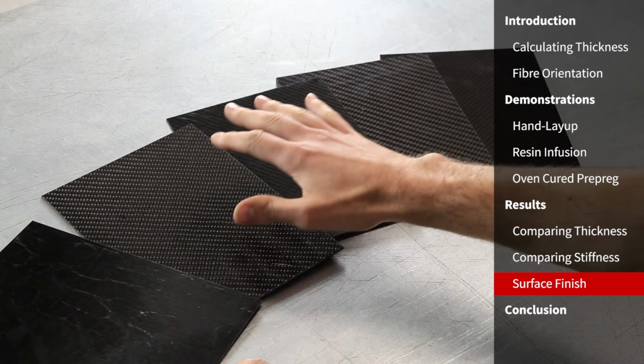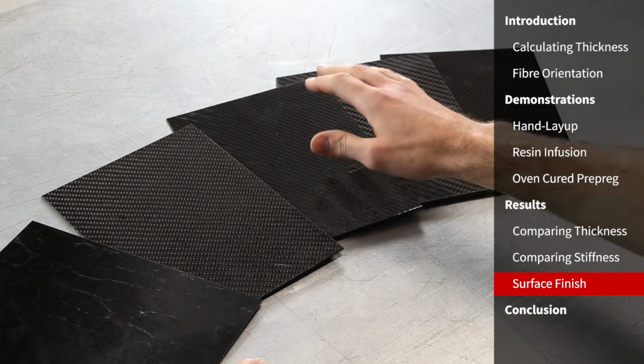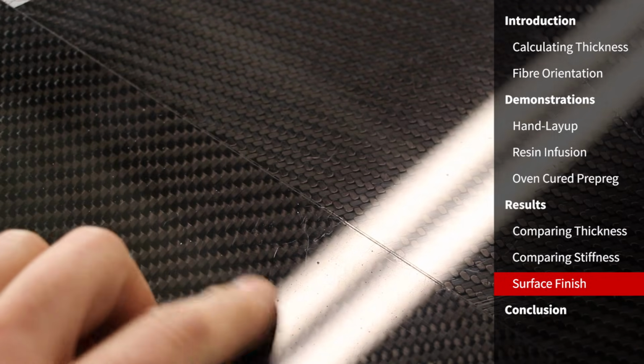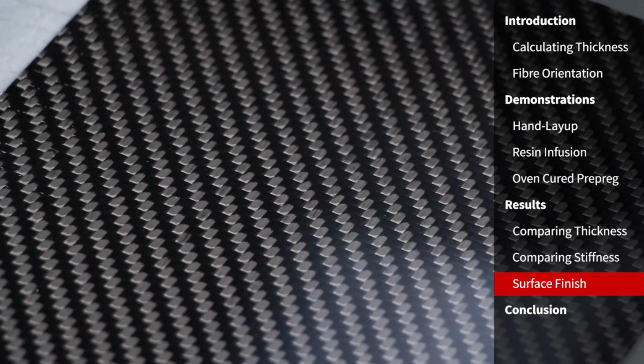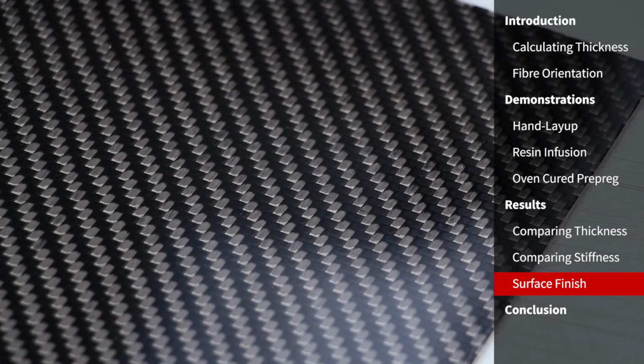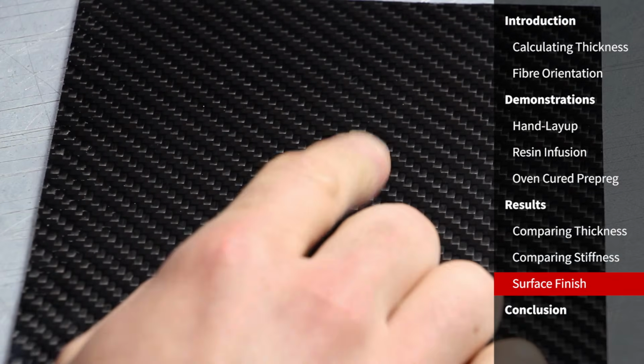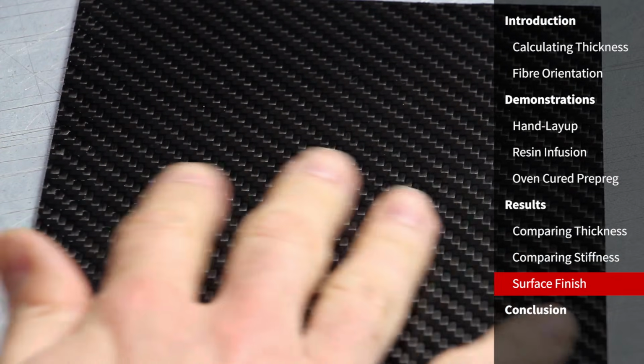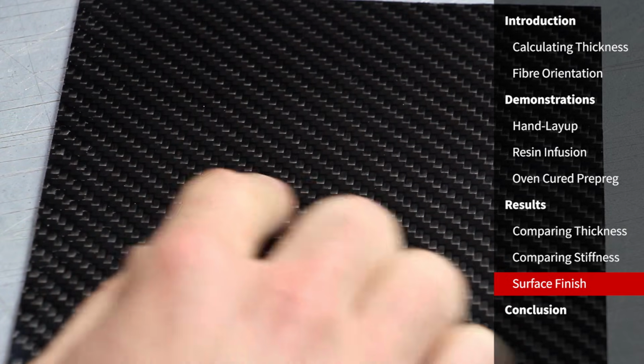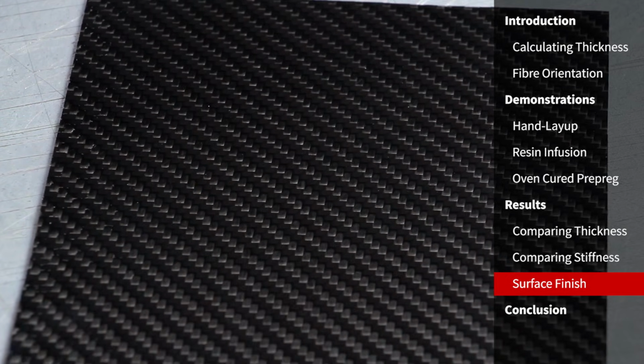Comparison between the wet lay sheet and the resin infused sheet. Both of them have got exactly the same surface ply, but the resin infused sheet has an absolutely perfect surface finish, whereas on the wet lay sheet it's pretty much unavoidable that you will get these tiny pinholes on the surface. Finally then, we've got our prepreg sheet. Not the easiest thing to show on camera, but as we've come to expect before from this material, we've got a fantastic cosmetic grade surface finish on this as well.